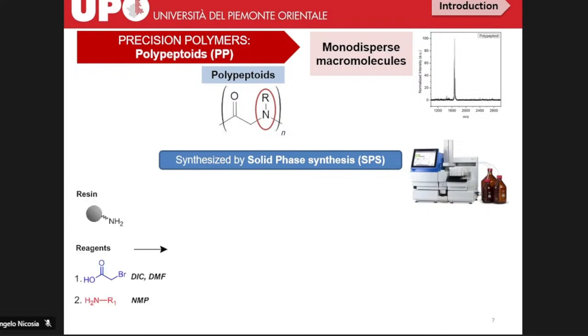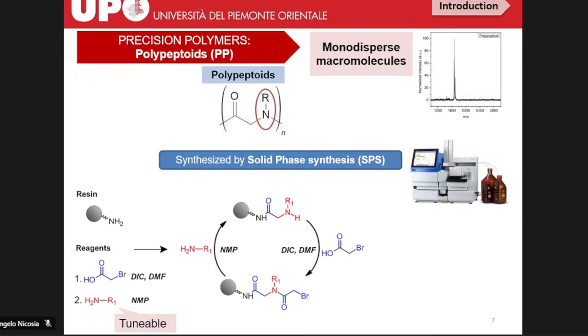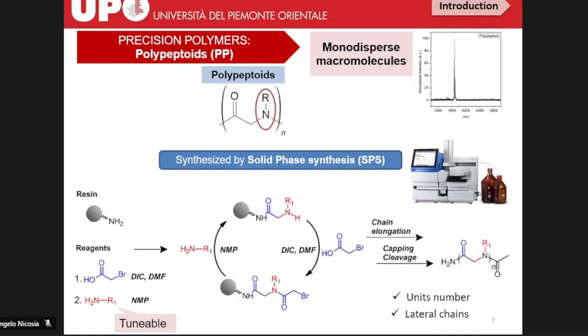Submonomers means that if I start the reaction from an amino-functionalized resin, instead of using an amino acid, I am using in the first step bromoacetic acid in the presence of a coupling agent, so I can form the amide bond, and then I have an amine that has a lateral chain that is tunable. It means that I can decide what type of amine I can add to my system. So if I repeat this process as many times as I want, I can finally obtain a polypeptoid where I control the unit numbers, but also I control the molecular architecture of my polymer.